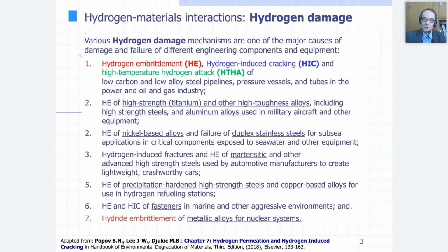When we talk about hydrogen materials interaction, the important industrial aspect is hydrogen damages. So you can see here on the slide in different colors various hydrogen damages. Hydrogen damage is a general term used for all of them, but actually hydrogen embrittlement, marked in red, is different from other hydrogen damage processes, hydrogen-induced cracking or high-temperature hydrogen attack. As you can see, hydrogen damage is one of the major causes of damage and very often catastrophic failure of different engineering components and equipment.